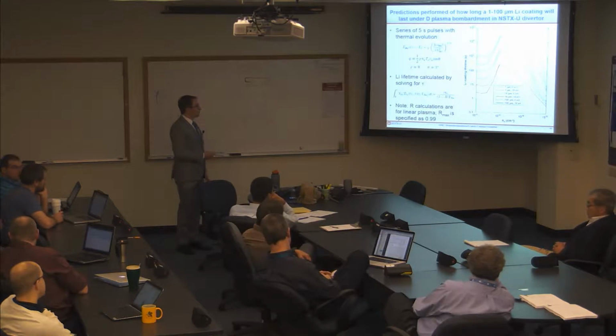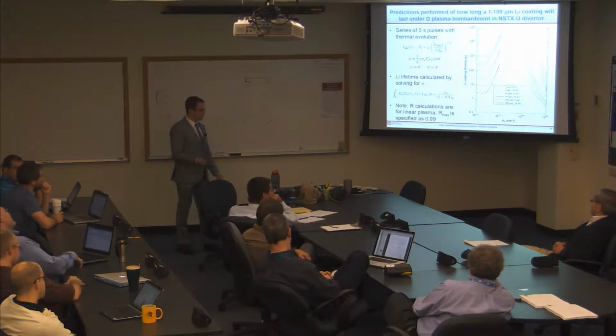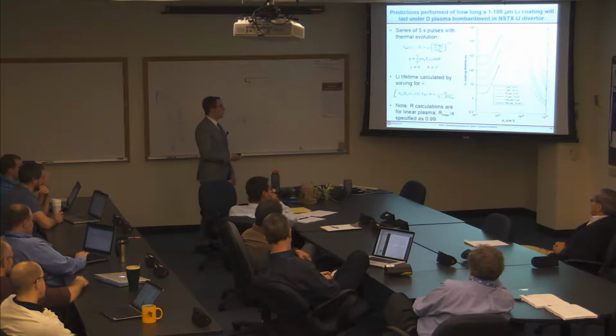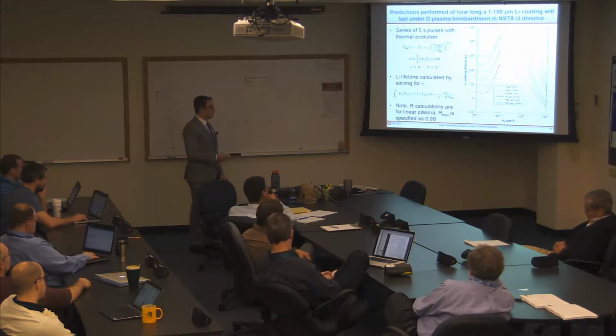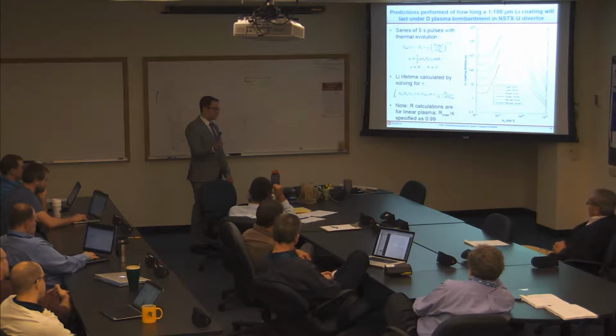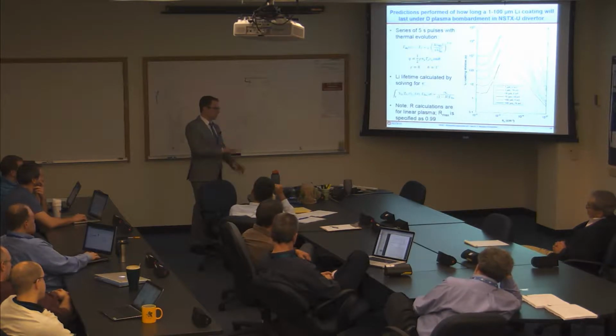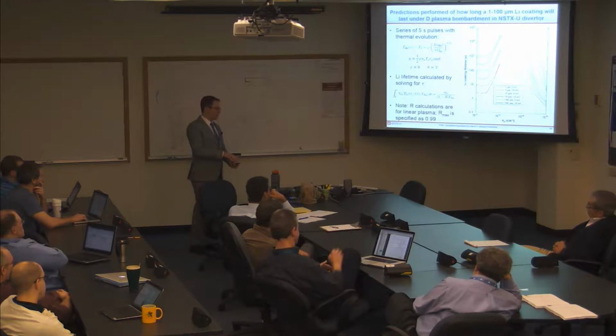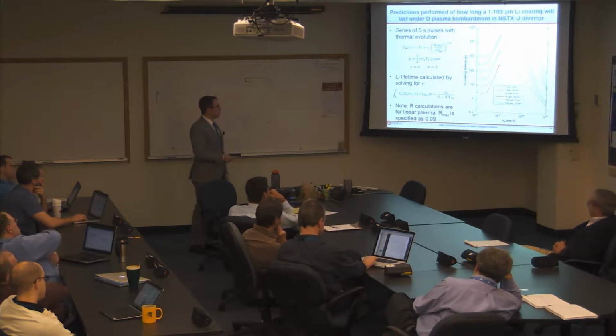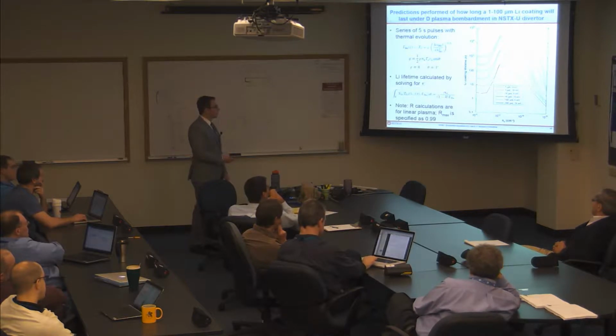And then you do the diffusion calculation along with the erosion calculation simultaneously, and include the redeposition fraction. So you incorporate all the aspects of the modeling and the prediction, and you dynamically model the deuterium concentration in the lithium surface as a function of time. And every time the lithium coating was reduced by more than 10%, I would revise the total thickness of the lithium coating and say that the rest had blown off into the plasma. This was a calculation that incorporated a lot of the elements of the theory of the modeling.